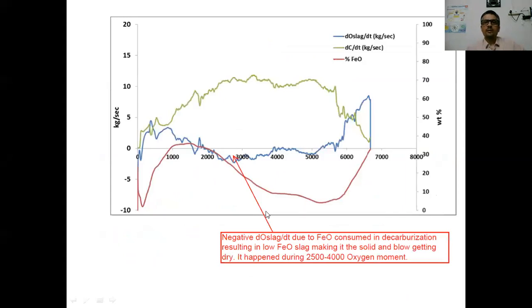Now, with the help of the dynamic control model, we can also predict dC/dt. As you can see, dC/dt has an almost theoretical-looking curve: initially it increases at a linear rate, then it becomes almost constant, and after that it starts decreasing. FeO initially increases, then it decreases. Please note that these are model-predicted results based upon the waste gas analysis of a specific plant's data.